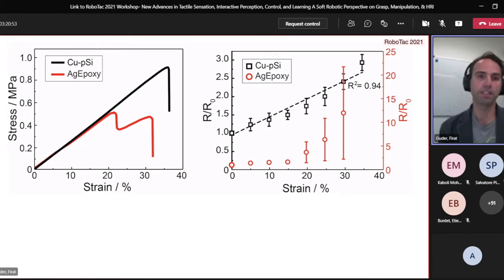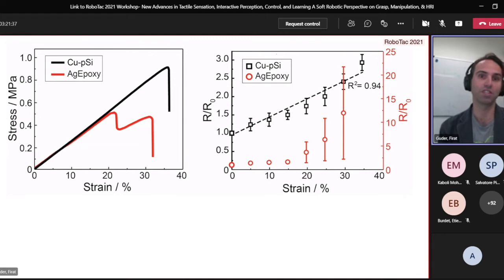And then when we stretch these materials, the silver epoxy essentially cannot withstand high strains. But not only that, it actually starts really breaking. So even if you think that you're getting a correct result, below 20%, it's not really working. This is also obvious when we look at the variability of the resistance measurements, because at the end of the day, these are just resistive sensors. We're just measuring the resistance of these conductive materials, which change with strain. And when we stretch these materials, we also see that the silver epoxy gives very high variabilities as we stretch them, and it's purely because the material is just cracking beyond some 15% strain.